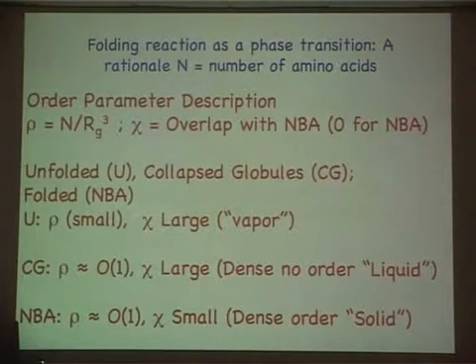Now, nominally speaking, you have the unfolded state and the folded state, but you can also imagine having a collapsed state which is not fully folded, in the sense that it hasn't acquired all the native interactions. So you would minimally require distinguishing between 3 quote-unquote phases: unfolded, compact, and native. 2 order parameters, and these are not by any means unique. One of them could be the density of monomers in this sphere of radius RG. So I define the density, which is the number of amino acids divided by the volume occupied by the protein, which is RG cubed. If you want, you can put in 4 pi over 3 or whatever.